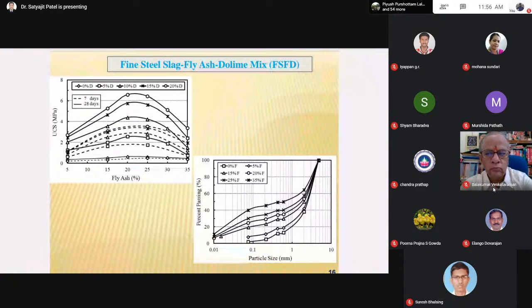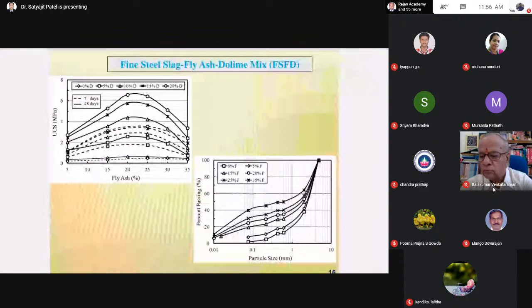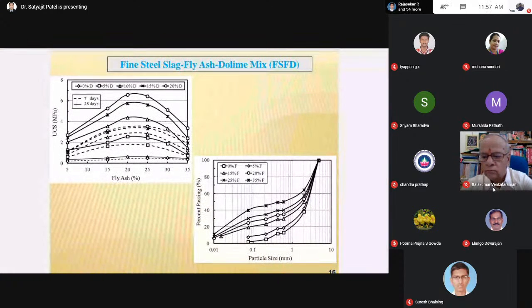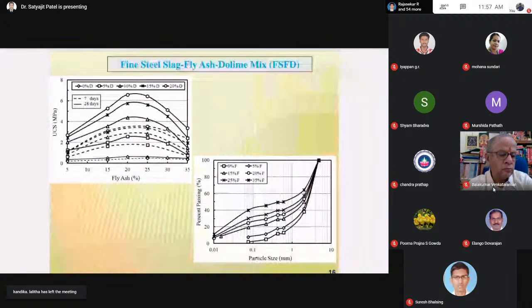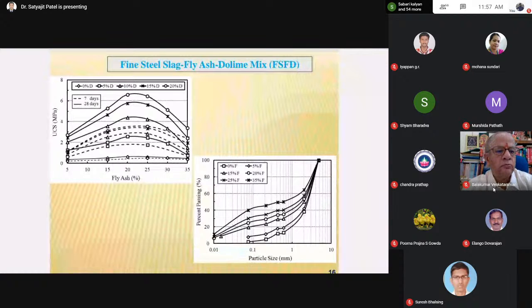So if you find out the requirement of IRC, for a cemented material to be used in the base layer, IRC recommends the minimum UCS value of around 4.5 MPa. Minimum 4.5 MPa UCS value should be there in the laboratory. 4.5 to 5 MPa should be there. So based on that, the mix of around 25% fly ash, 20 or 25% fly ash with dolime content of 15% fulfills this IRC criteria, which indicates that this mix can be selected as the optimum mix for use in the base layer.